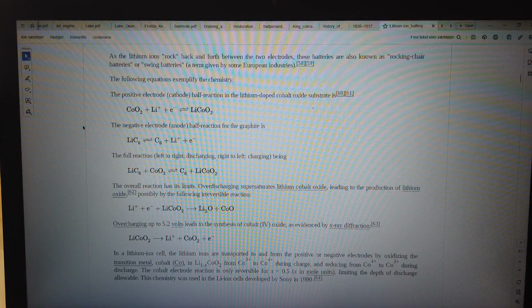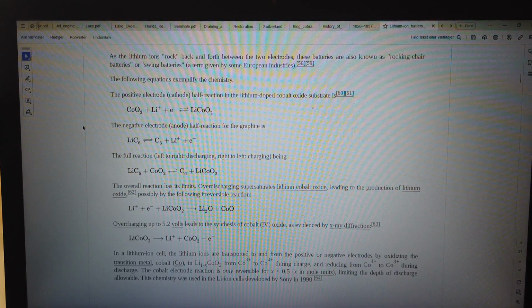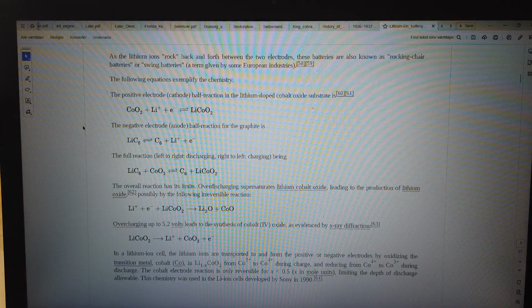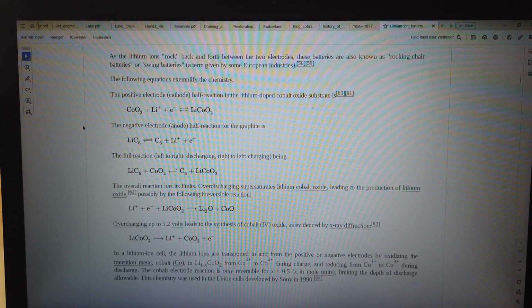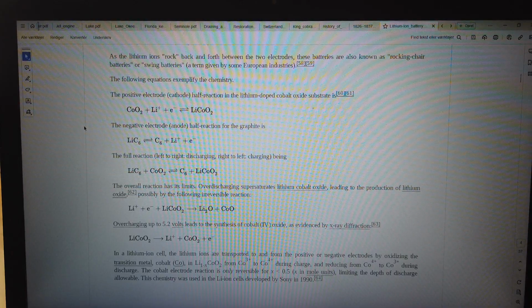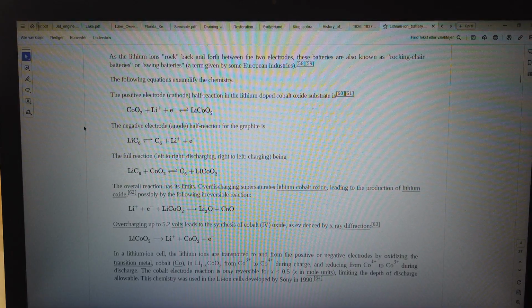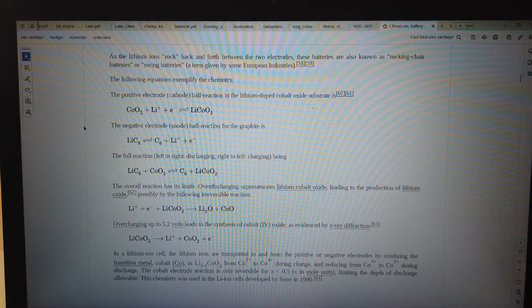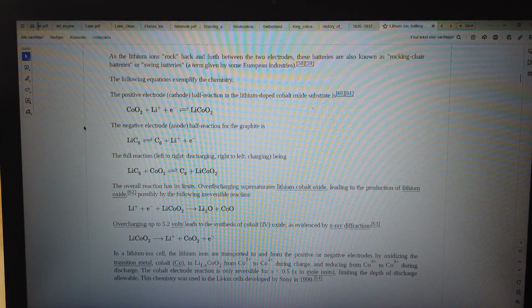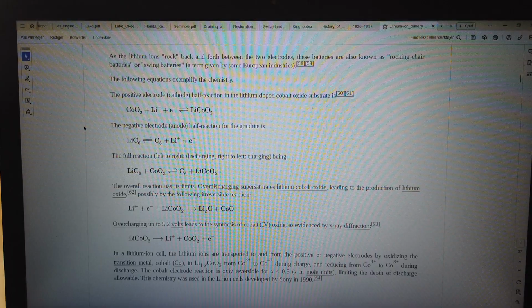Overdischarging supersaturates lithium cobalt oxide, leading to the production of lithium oxide, possibly by the following irreversible reaction. Overcharging up to 5.2 volts leads to the synthesis of cobalt(IV) oxide, as evidenced by X-ray diffraction, in a lithium-ion cell.